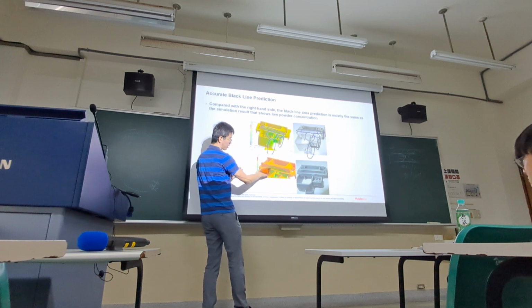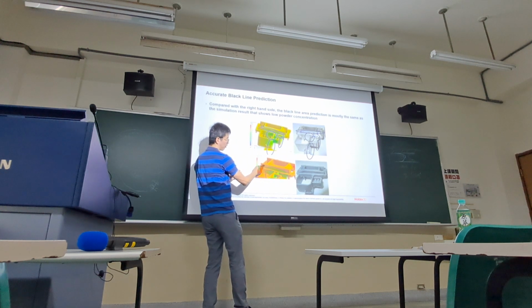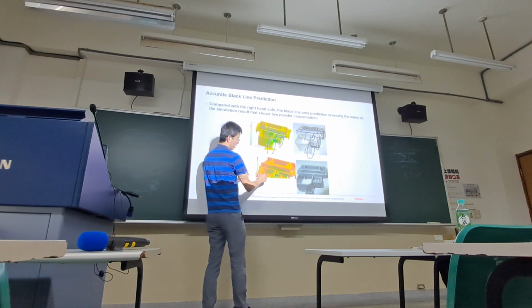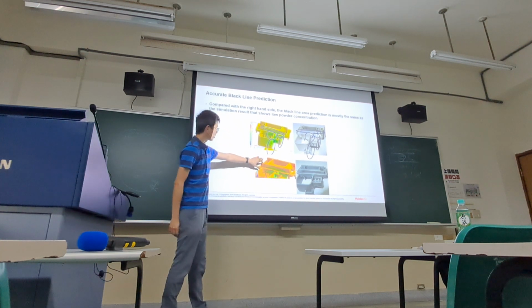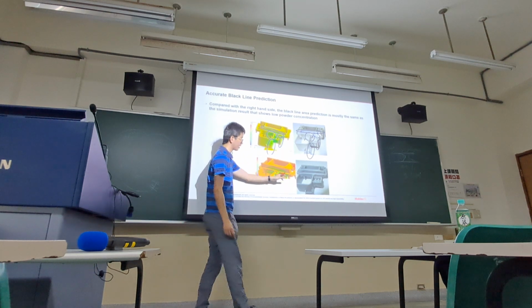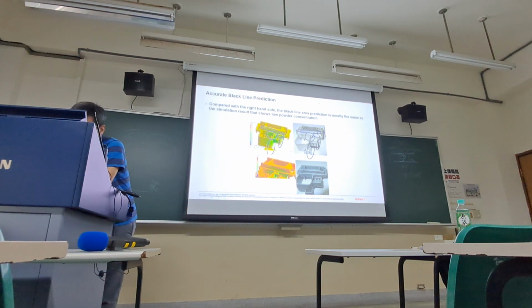And with the simulation software, you can identify that this concentration is quite different from this one. So there is some edge. And we can see from the concentration result, those lines are identical to the experiment. And not just for the green part, if you sinter to have the final part, those areas may have poor properties.